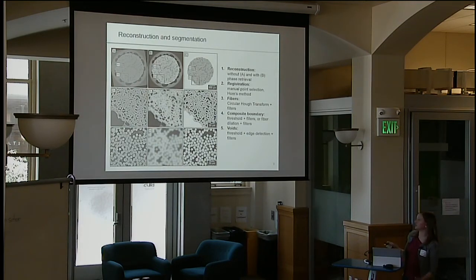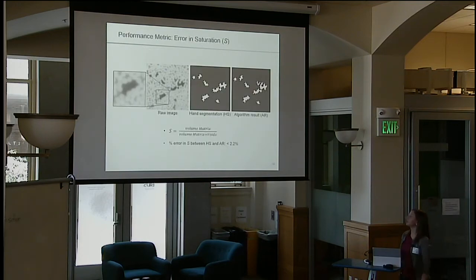So after we have this complete segmentation, which has been optimized fairly carefully with several filters and testing of different parameters, then I want to see: is this good enough for the science that we want to do? The performance metric that I've been using in these segmentations is the error in the saturation that we measure from the 3D images. The saturation is just the volume of matrix over the total volume of matrix plus voids. For all of the data sets that we've analyzed, I do one hand-segmented slice, and I found that the maximum error is about 2.2%, which is pretty good for about 100 different volumes that are all large and have varying artifacts across the experiments.